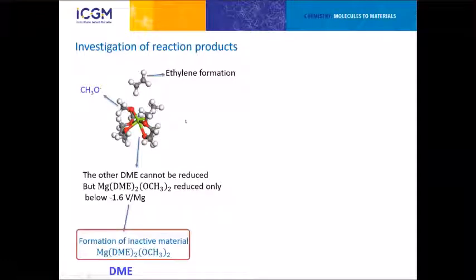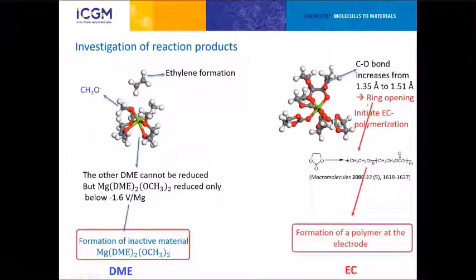When we look more closely at the reduction process for DME, we directly see ethylene formation and methanol. Once we get these species, the problem is they cannot be reduced anymore. The reduction potential of methanol, computed versus magnesium, is very low. So that means we are creating a mostly inactive material. The consequence of the solvent reduction in this case is the creation of inactive material, which is certainly going to precipitate at the electrode.